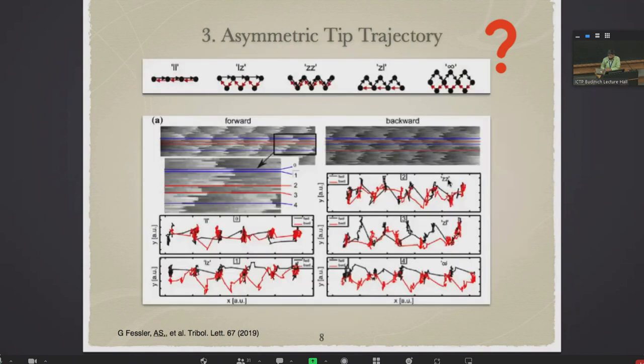Perhaps one expects that in both directions the dissipation should be the same, but Gregor showed that actually, as is seen in this profile, the black one is for forward, the red one is for backward, and this panel is for line number one. The direction of the sliding is important and the dissipation differs in forward and backward, and it is not by accident. There are so many scanning lines that show this asymmetry. It's the second interesting question. And also a third one, which is perhaps related to the previous two ones, was the asymmetry of tip trajectory.